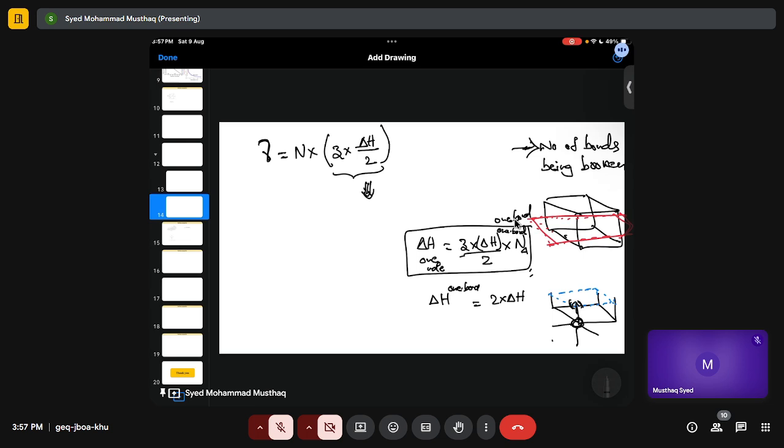Because it is just the delta H of melting, right? That's what we are trying to do. Delta H of melting is nothing but loosening that bond from solid to liquid. The liquid atoms can easily move, but not the solid atoms. So we are trying to break the bonds of solid atoms when we heat from solid to liquid. So that's why this will be delta H of melting, and this is a standard value. We can get it anywhere. Times divided by coordination number into NA.